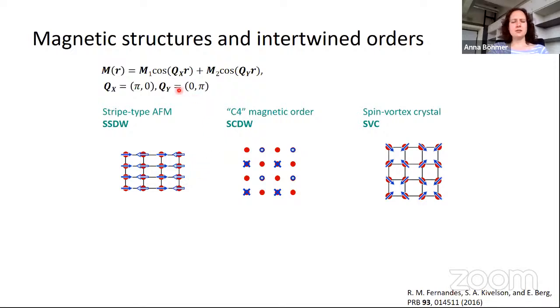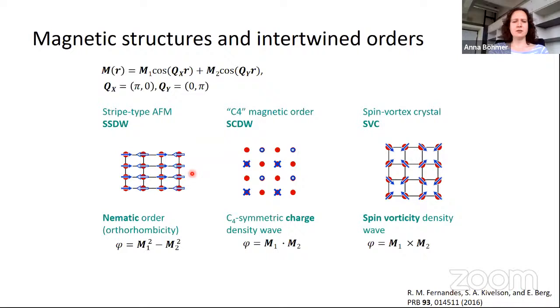In these iron-based materials, we have complex magnetism that can be described in this way, and we find three options, three different patterns coming from the same mechanism, same wave vectors. We find the stripe type with the interesting coupling to the structure and the nematicity. We find the spin charge density wave, this alternating one, where moments sometimes cancel. And we found the spin vortex crystal where moments rotate within the plane. Each time there is some new emergent order parameter, which is a concept in this sort of physics, which sometimes we can measure easily and sometimes we can't.